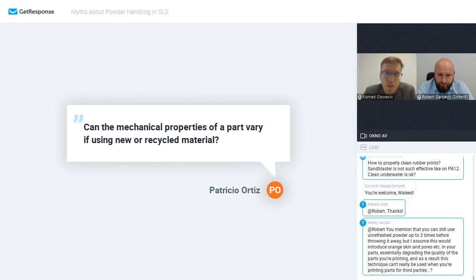Okay. Can the mechanical properties of a part vary if you're using new or recycled material? Essentially, at the beginning you might get slightly better mechanical properties, but it will stabilize. The values we provide are stabilized values that we tested after at least 5 cycles, between 5 to 10 cycles. And for PA12, those are results that we got with material that has been in the loop for 2-3 years now. So we are certain that these are stable values. At the beginning, you might get better values than that.